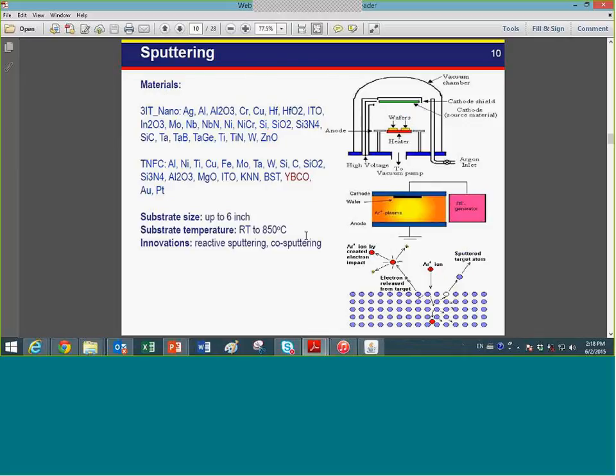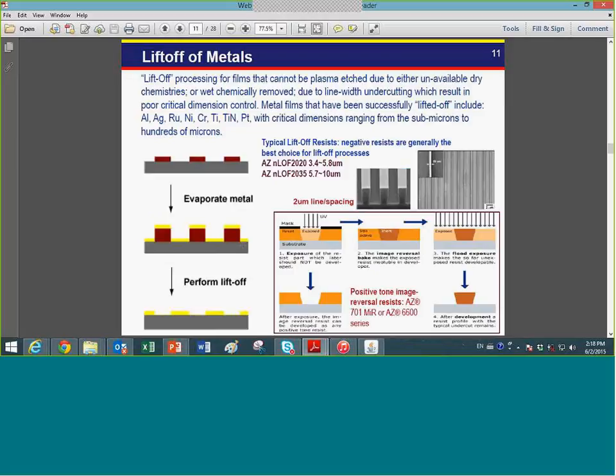And for sputtering, we have a new sputtering system through AJA International, going up to 6 inch, and the substrate temperature goes up to 850 degrees Celsius, and it can do reactive sputtering or co-sputtering. So these are the materials we have right now, excluding YBCO, but this system can allow us to deposit YBCO superconductors at high temperatures. And the 3IT, for example, can do all kinds of these materials as well.